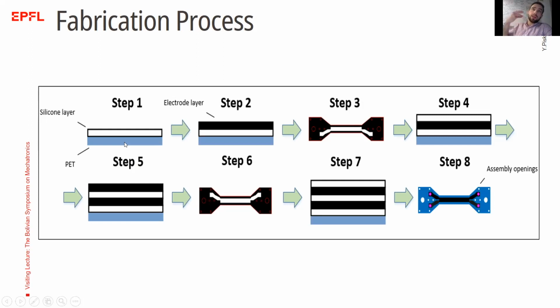Then on top of the PET layer, we pour some liquid silicone. Then we plate cast it, so we make a really thin layer out of it. Then we put it in an oven. That's how we form the first layer with a thickness around 100 microns, okay? Then after that, we put on top of it a layer of conductive silicone, and then we put it in an oven. The thickness of this layer is around 20 microns, so it's an extremely thin layer. After that, we go to the laser cutter and we actually etch the surface.